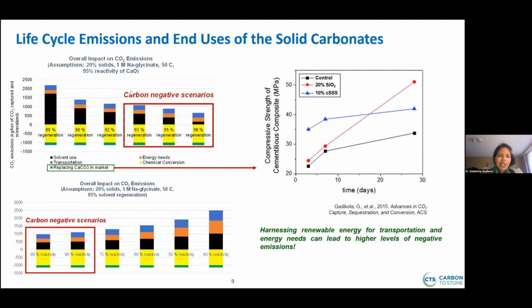Now, in terms of LCA, we can take a look to understand the levers that we can effectively tune to achieve more effective carbon removal. So here we looked at solvent use, we looked at transportation, we looked at replacing calcium carbonate in the marketplace, so replacing natural calcium carbonate with anthropogenic calcium carbonate. We looked at energy needs and chemical conversion. So we have positive emissions and we have negative emissions. And what you'll notice is that we actually start getting to carbon negative scenarios if you're able to regenerate and recover more of the solvent per cycle.